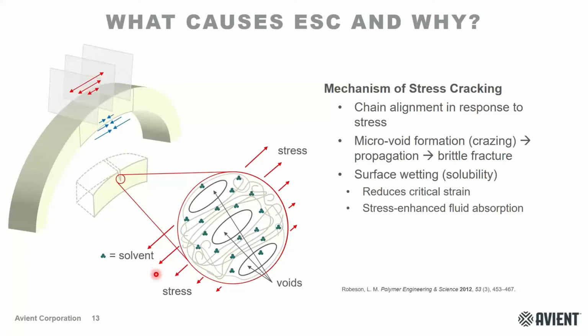And so when that solvent gets in there, it increases the free volume, it increases the mobility of the chains, suppresses the glass transition of the material. And sometimes, for example, in an amorphous material, the solubility of the diffusion of the solvent into that amorphous material can actually create osmotic pressures that impart even more stress to the part.